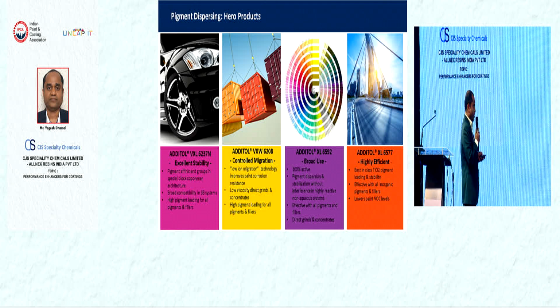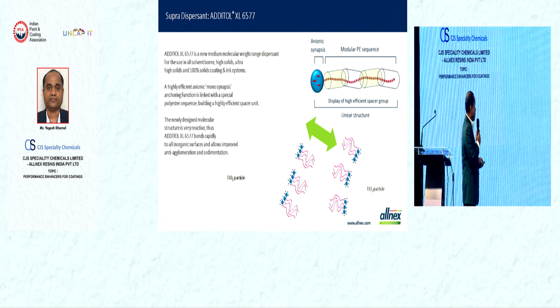Then this ADDITOL XL6577, which is a highly efficient, best in class inorganic pigment dispersant. On next slides, you will come to know why we are calling it a supra dispersant. So ADDITOL XL6577 is a new medium molecular weight range dispersant for use in solvent-based, high solids, ultra-high solids, even solvent-free systems. From a chemistry point of view, it is a highly efficient anionic synapses anchoring function, as you can see here in the structure, and that anionic anchoring function is linked to the modular polyester sequence, and this modular polyester sequence builds a highly efficient spacer unit, and that's why the dispersed pigment particles don't come into contact with each other for agglomeration or re-agglomeration.